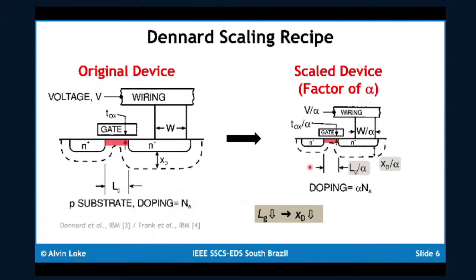As you scale the gate length, obviously the depletion regions associated with the source and drain to body junctions need to get thinner, and that necessitates the body doping to increase. Unfortunately, increasing the body doping causes the threshold voltage to increase, which necessitates the oxide thickness to go down to recover some of the gate coupling and reduce your threshold voltage. And since we are now having thinner gate dielectrics, that requires the supply voltage to also scale down to make sure that you don't have issues with dielectric breakdown.